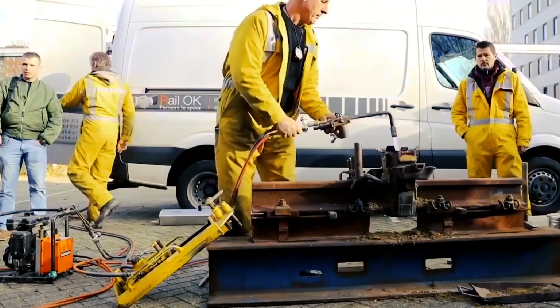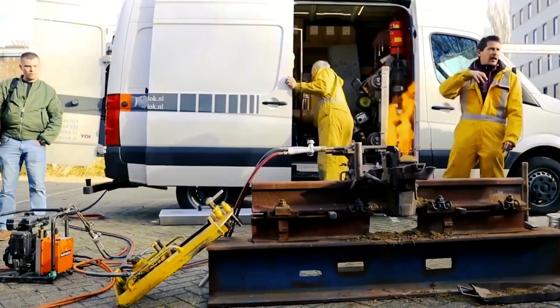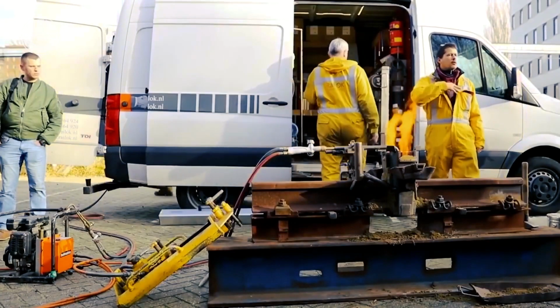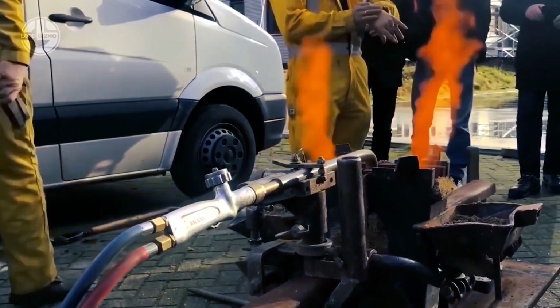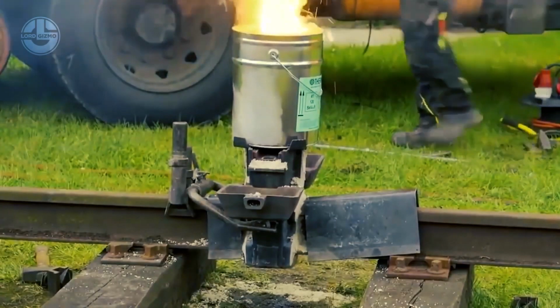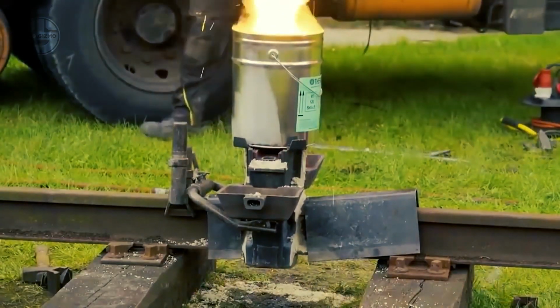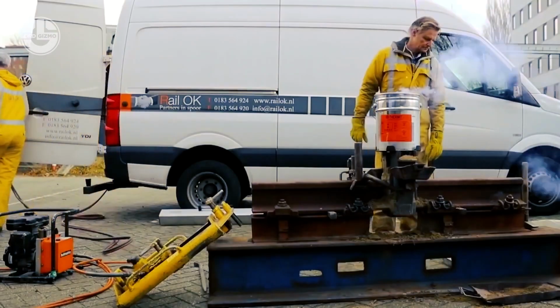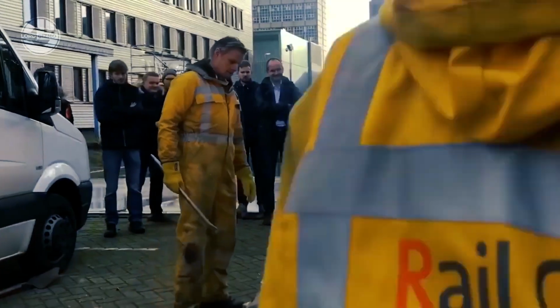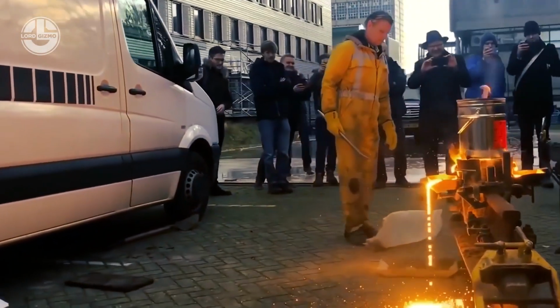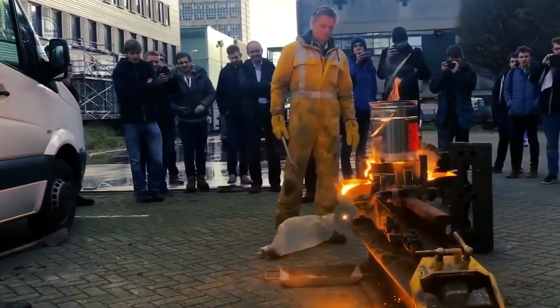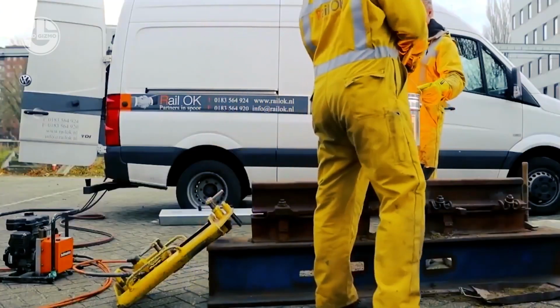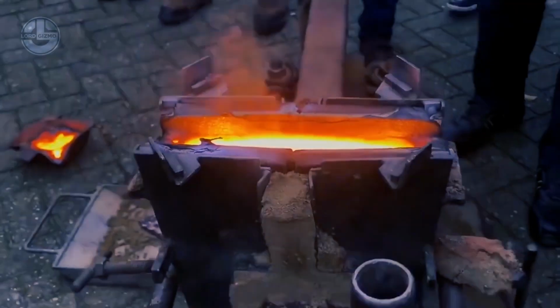This portion will focus on thermite welding. Whenever they're tasked to weld railway rails together, one of the techniques they use is thermite welding. It's called thermite welding because it uses a mixture of iron oxide and aluminum powder, which is called a thermite. In this process, they use a temperature of at least 3000 degrees Celsius to begin welding. Here's a step-by-step process of how they do it.